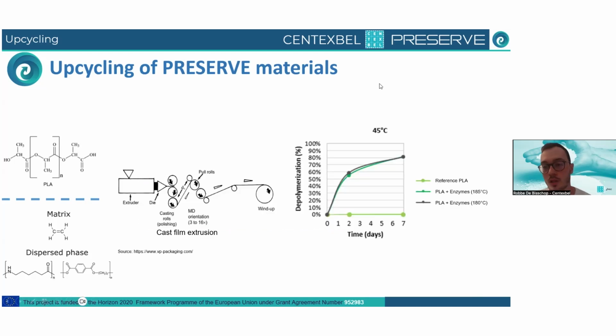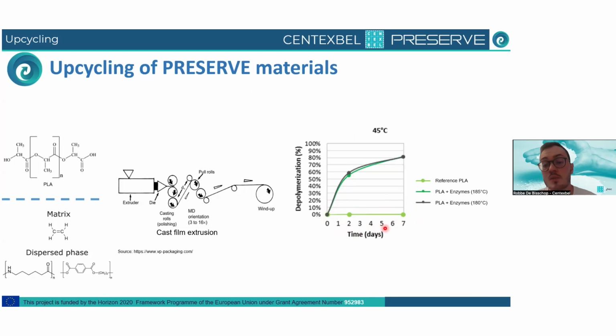And then there are 2 things that I will not be talking about in this presentation, but I just want to mention them as well, because there are very interesting results also from the Preserve project. One of them is using enzymes in the PLA, which will create a very good biodegradable PLA that is much faster biodegradable. You can see here, I will use my laser pointer, this graph, the light green one, which is the reference PLA, just a standard PLA. And when we add 5% of enzymes, you can see that the depolymerization is already very fast, very broad. And we will try to get to home composting conditions. Research is still ongoing at OWS to look at the real biodegradation results. But as they take a lot of time, we are still working on them. But I just wanted to mention this.